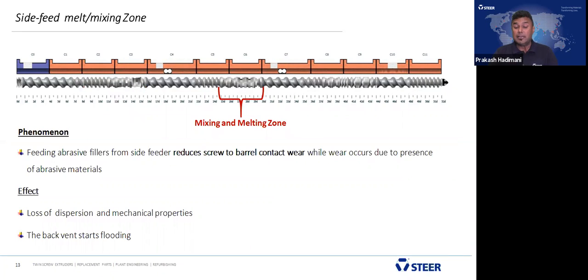Now we move to the next section, the mixing and melting zone. After the polymer is 100% molten, we try to feed talc from the side feeder, and then mixing and melting has to take place again in that section. What phenomena happen there? The mixing and melting takes place, but the feeding of abrasive materials, some fillers, from the side feeder reduces the screw to barrel contact, and wear occurs due to the presence of abrasive materials.